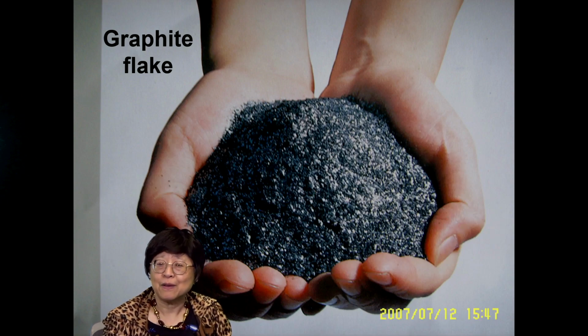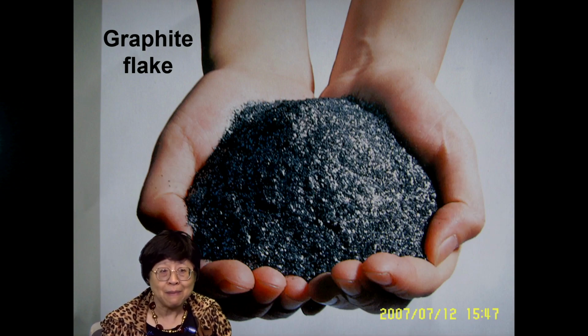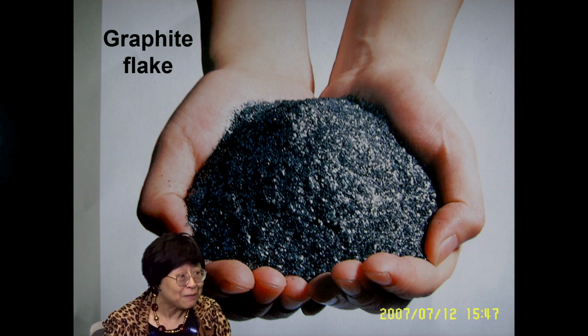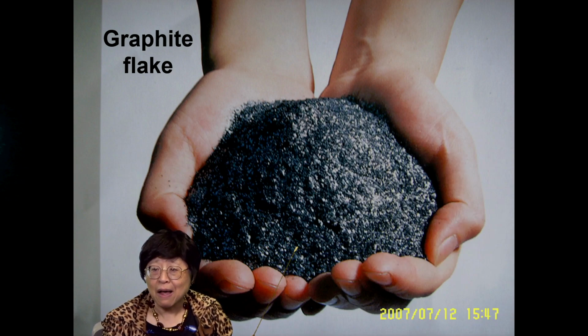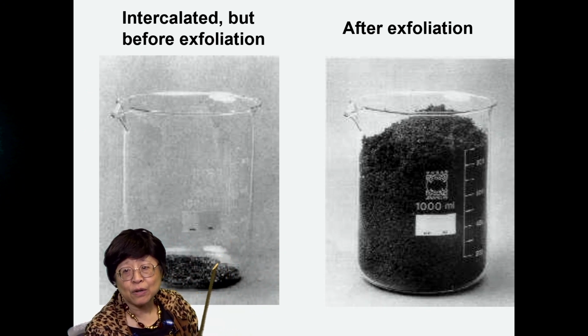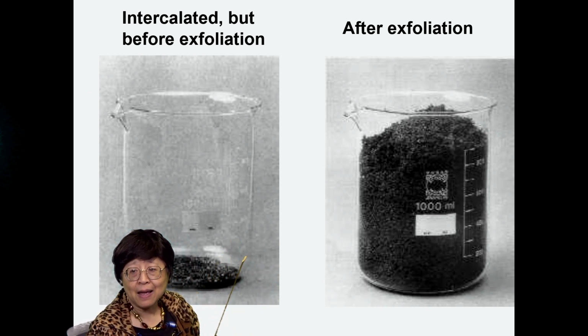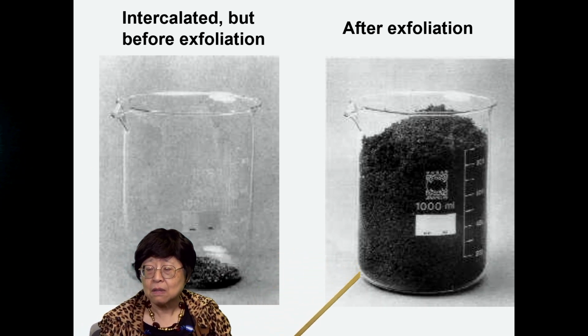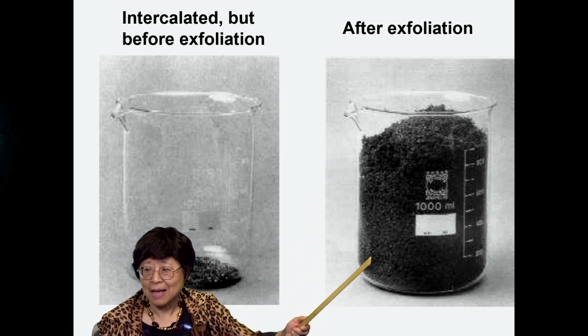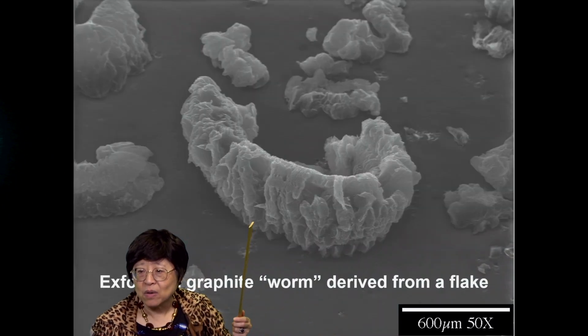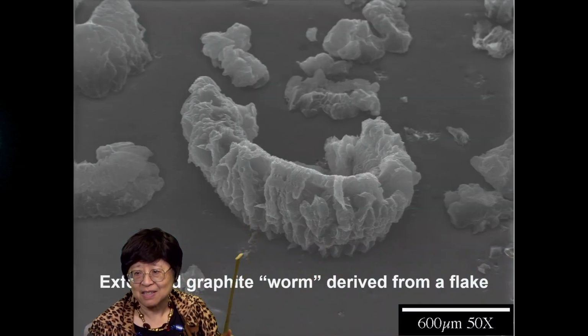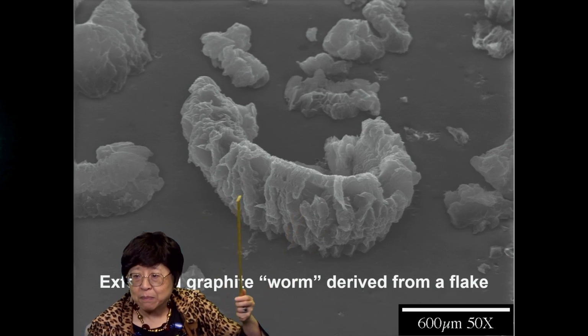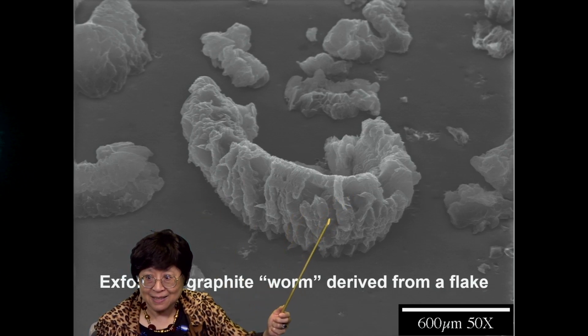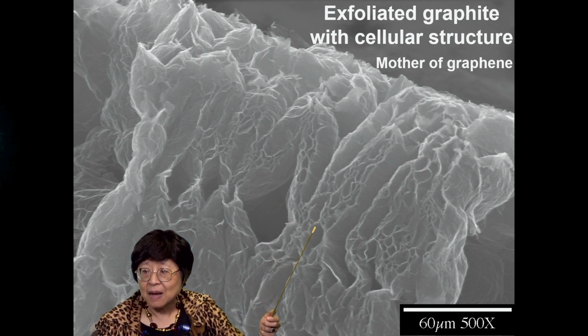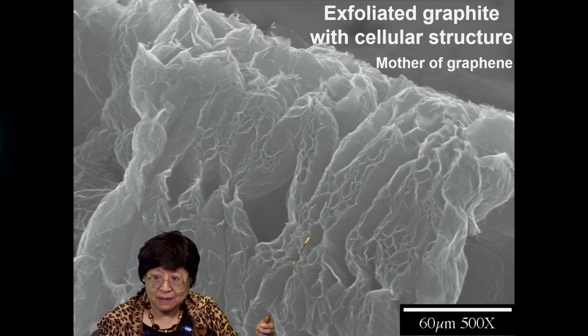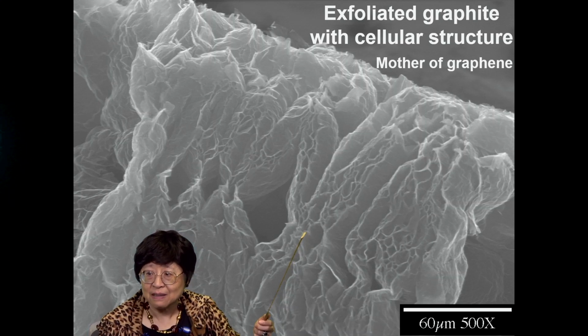To push this even further, we went to yet another route to maximize the surface area while having the conductivity. And we used graphite flake. And we intercalate the graphite flakes and then rapidly heat that, and that caused puffing up, exfoliation. And this exfoliated material, which we call worm, because it looks like a worm, this one piece of the worm is derived from one flake. You see there's a cellular structure. And this is actually the mother of graphene. You can shake this loose to make graphene.